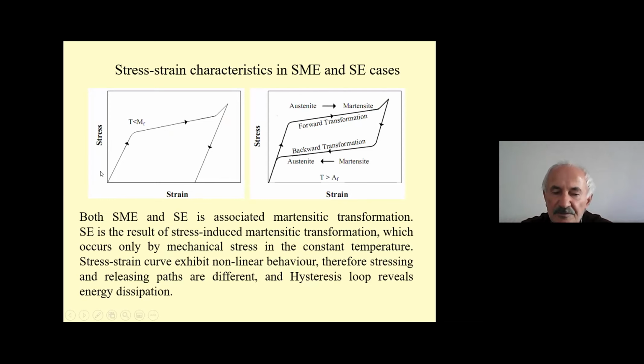In the shape memory effect, the material is deformed in the low temperature condition. This is plastic deformation, and the martensitic material keeps the deformed shape after releasing. As you can see, the early stage of deformation exhibits ordinary elastic material behavior, and stress-induced martensitic transformation occurs at the plateau level. In superelasticity, stressing and releasing paths are different, and hysteresis loss refers to the energy dissipation.